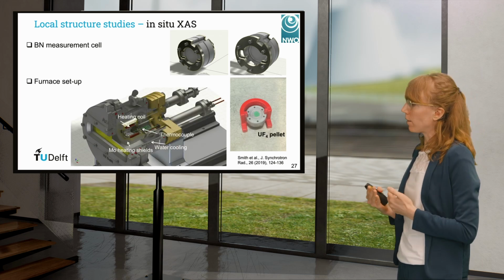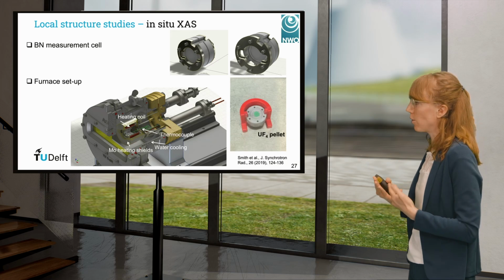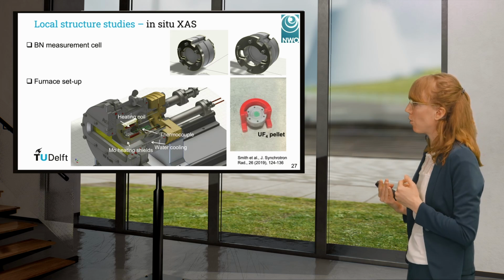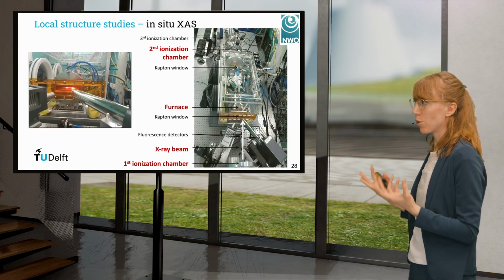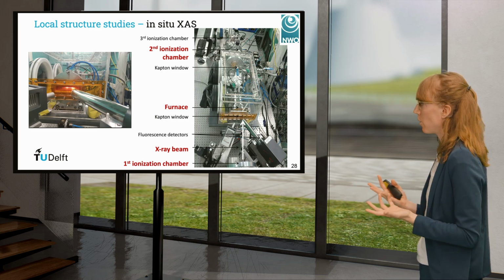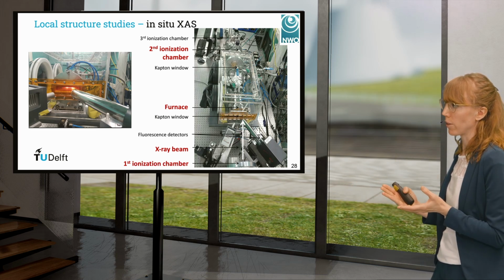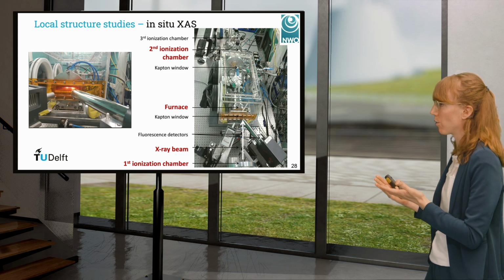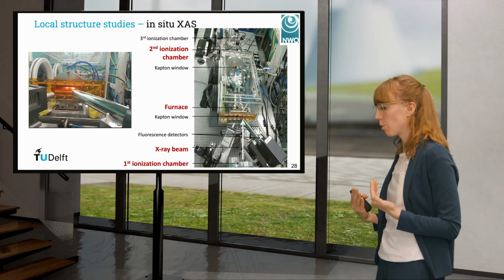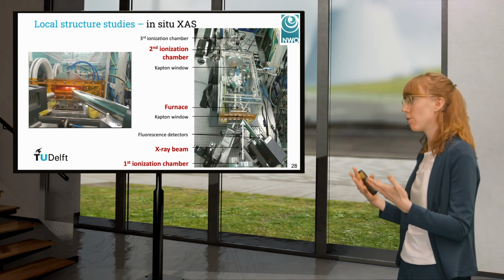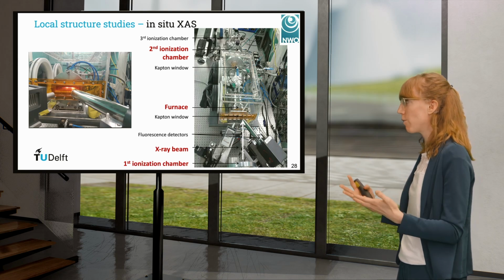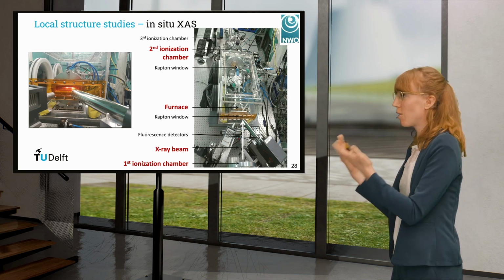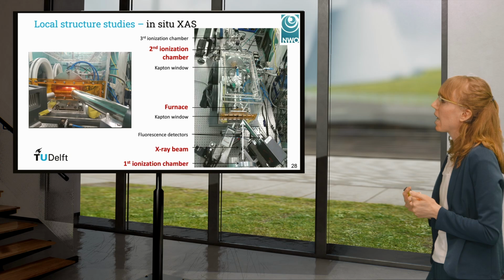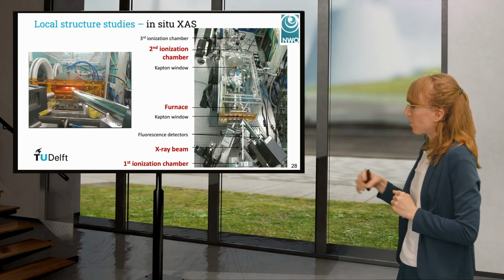Because we need to heat up the salt so it is liquid, we also designed and built a furnace. And to make sure nothing comes out, since these are radioactive salts, we also have a glove box around it, which we also built ourselves. So when we do these experiments, we go to the synchrotron facility with the cells, with the furnace, with the glove box, everything in the car, and then we get to the synchrotron. And we can start the experiments.